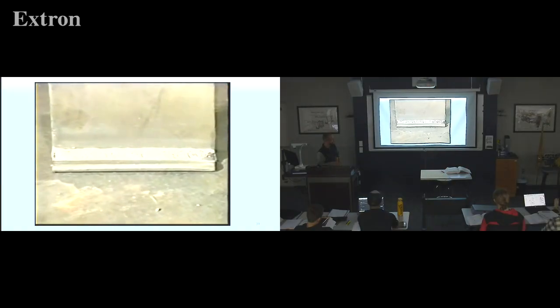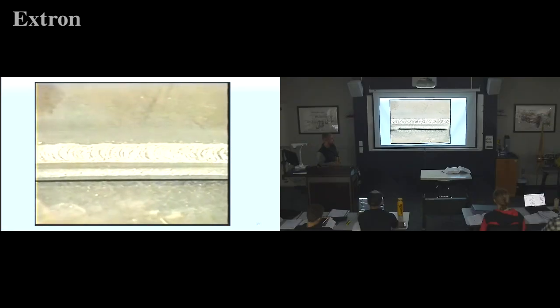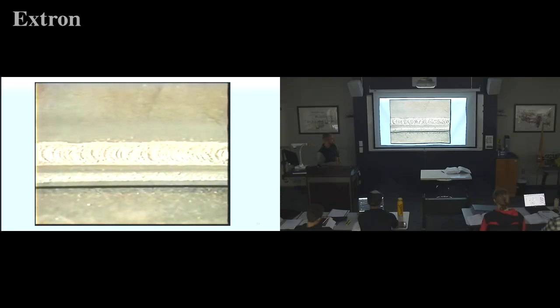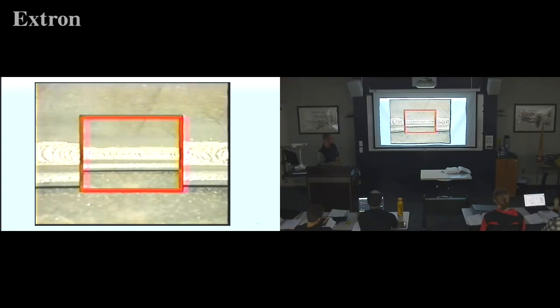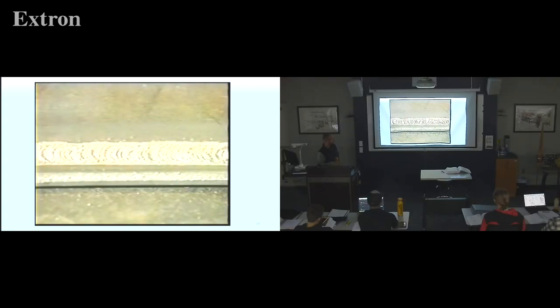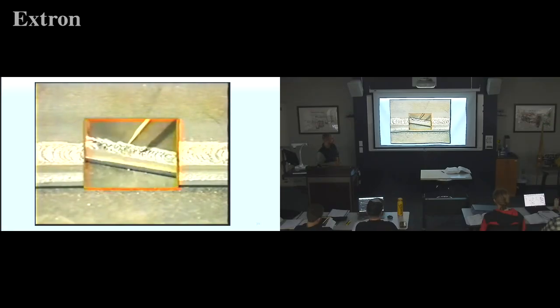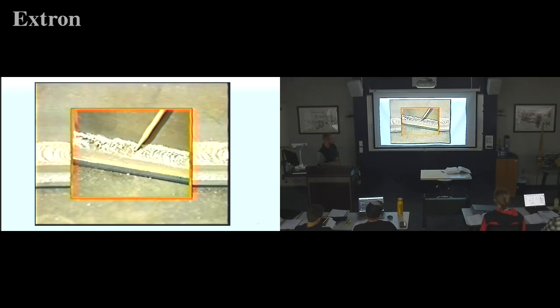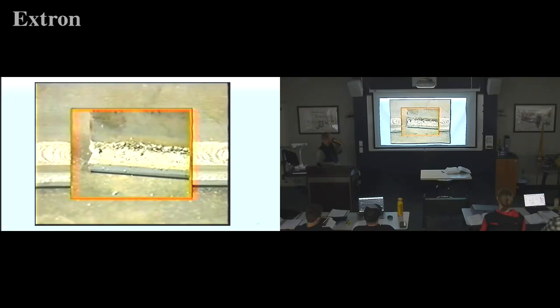and visually inspect the completed weld. The standards of acceptability are: the weld shall be acceptable by visual inspection if it shows that the weld has no cracks. The weld must show complete fusion between the weld metal and base metal. There shall be no slag inclusions exceeding 1/8 inch in any 6 inches of weld. There shall be no porosity exceeding 1/16 inch maximum, and the weld shall have no more than the combined total of 1/8 inch in any 1 square inch of weld.